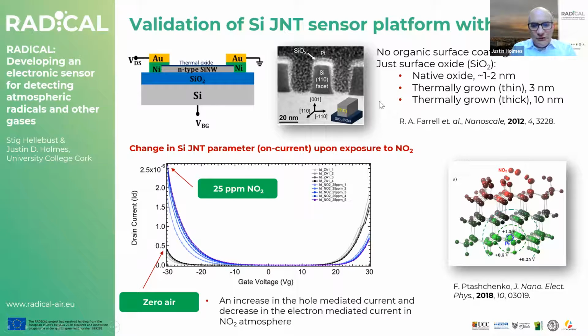This image in the middle shows a cross-section of a silicon nanowire. On the top of this wire, I don't know if you can see my cursor or not, we're just changing this SiOx layer. We're changing its thickness and looking at the response from our devices. We have a native oxide which grows naturally on the silicon, around 1 or 2 nanometers, and then we can thermally grow a thin oxide layer, say 3 nanometers, or a thick oxide layer, which is 10 nanometers. We want to see if the interaction with NO2 at the surface gives us any change in signal in our device. This is based on a lot of theoretical studies where researchers have looked at the interaction of NO2 with silicon surfaces, and you see this dipole moment change. And down here in the bottom left is a plot of drain current versus gate voltage.